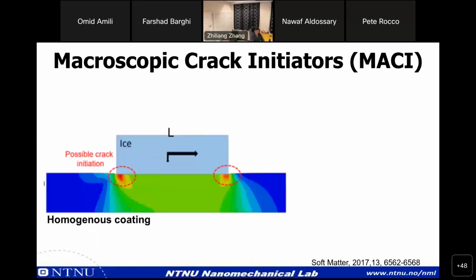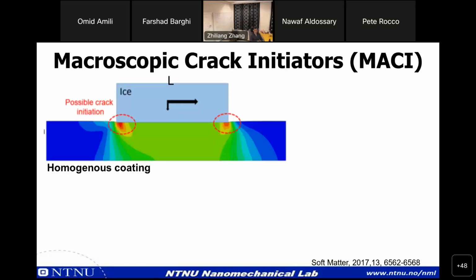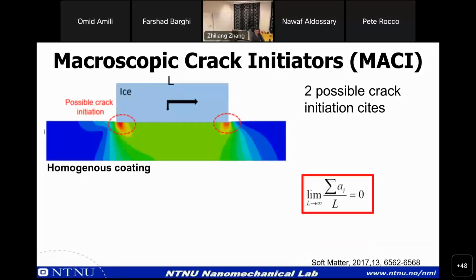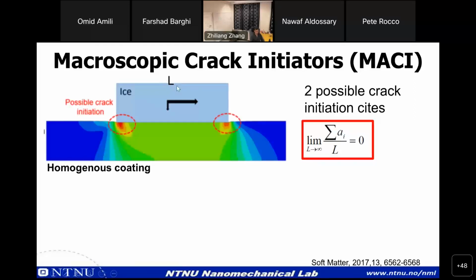So we can theoretically prove this MACI concept. For the homogeneous coating, homogeneous surface, if there are no subsurface structures, usually for a 2D problem, we have 2 crack initiation sites. So a crack could possibly initiate here on the left and here on the right, the 2 initiation sites. If the length of the ice becomes larger, the total crack length over the ice length, when the length approaches infinity, becomes 0. So the crack length could be neglected.